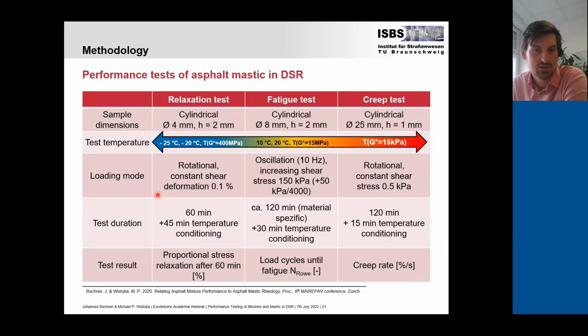For the relaxation test, we had a constant shear deformation of 0.1%. For the fatigue test, we use an oscillation test with increasing shear stress. For the creep test, we use a constant shear stress. So kind of using the broad variety of the DSR for application. I will demonstrate the 3 different tests in the next slides.